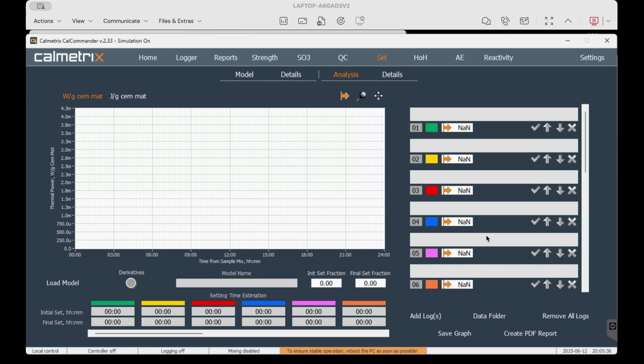Yeah, well, that 1/3, 2/3 is from years of experience, and ASTM C1753 has others because it's written by someone else who also has years of experience. None of them is bad or good. The reality is, in the ascendant phase where the curve goes up before the main peak, the steeper it is, the more irrelevant it becomes to argue whether it's 0.21 or 1/3, because when it's quite steep, a slight change in the ratio will not induce a lot of change in the time. If you look at a very steep curve, you can be quite wrong in the ratio, and it will not change a lot on the x-axis in terms of time.